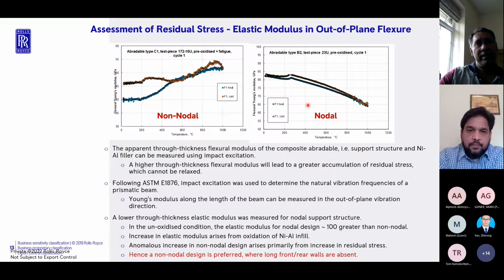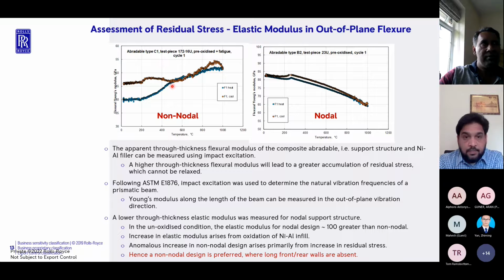And if you looked at the elastic modulus in out of plane flexure in the unoxidized condition, the non-nodal design has almost 100 times lower elastic modulus compared to the nodal design. Now, I've not shown that graph here, because the graph I've shown here is in the oxidized condition. But even in the oxidized condition, you see at least about a 20 to 30 gigapascal lower elastic modulus in the non-nodal design compared to the nodal design.